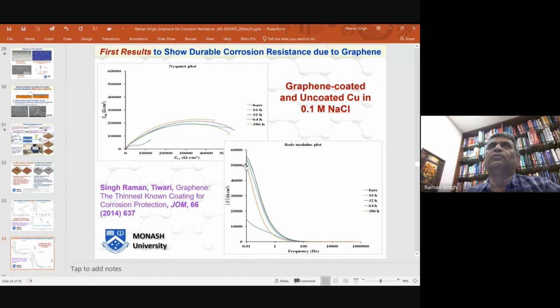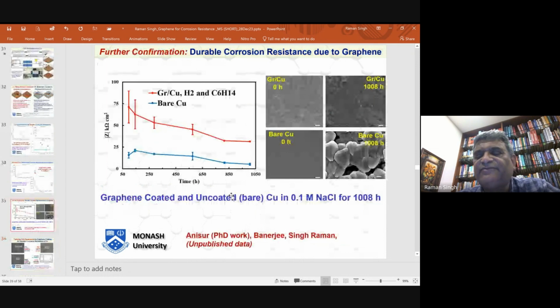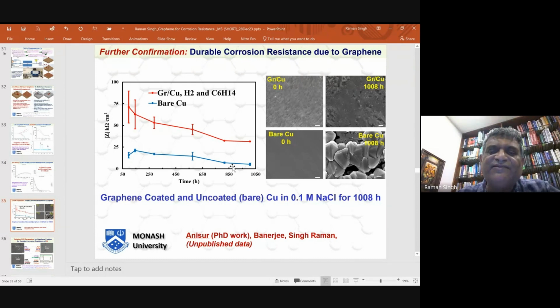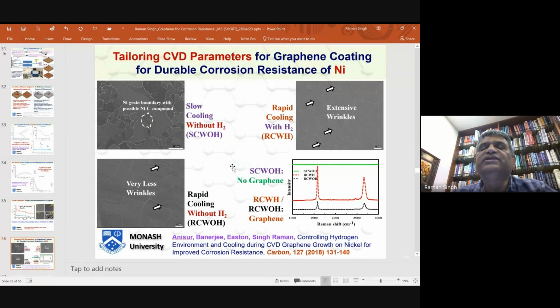So first time we could show that if you had proper graphene, and in this case it was multi-layer graphene, the corrosion resistance is durable. That is unlike what was reported in those two publications in very reputable journals. So first time we could show that yes, you can have durable corrosion resistance. Later on, we improved the CVD, or chemical vapor deposition parameters, and we could show that graphene on copper can give longer term corrosion resistance. But keep in mind that we had our interest in developing multi-layer graphene, which is easier. Developing multi-layer graphene is easier on nickel. So our future work primarily focused on nickel.